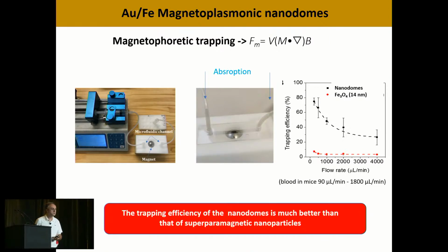And then we wanted to make sure that these nanoparticles could be manipulated using magnetic fields. So we made a simple microfluidic system where you can see here, this is a magnet, and here we enter, the liquid goes on top of the magnet and then goes out on the other side. And what we did is we measured the optical absorption on this side before they go through the magnet, and then we measure again the optical absorption after they go through the magnet. In that way, we can know roughly the concentration just by looking at the change of optical absorption. And then here you can see we inject this at controllable